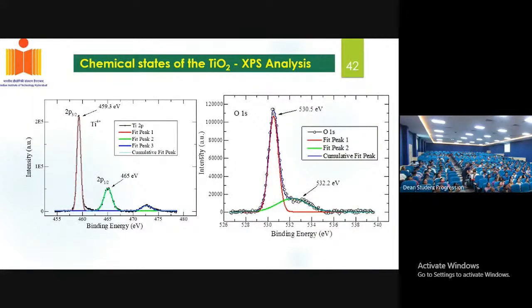We have also done the XPS, the X-ray photoelectron spectroscopy study. This will give information about the different valence states that the elements have. As you can see here, we could see the titanium 4+ state and the oxygen 2- state in our device.